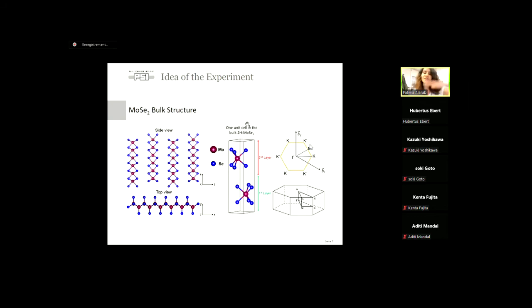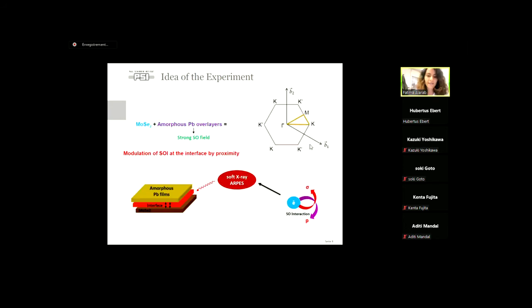So there's the van der Waals interaction between the layers, a weak interaction, which makes it very easy to, for example, cleave the system and get single layers or monolayers, for example. And this is what many people are doing. So this system, because it contains molybdenum and selenium, the high Z element, so basically it has a spin-orbit coupling, intrinsic one.